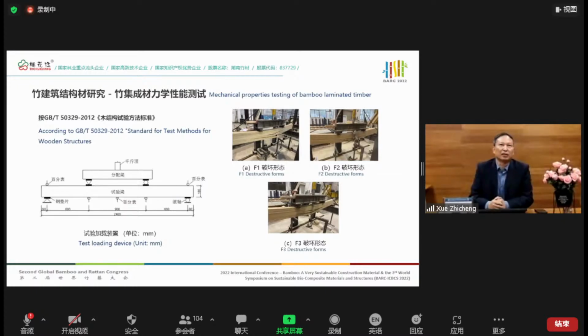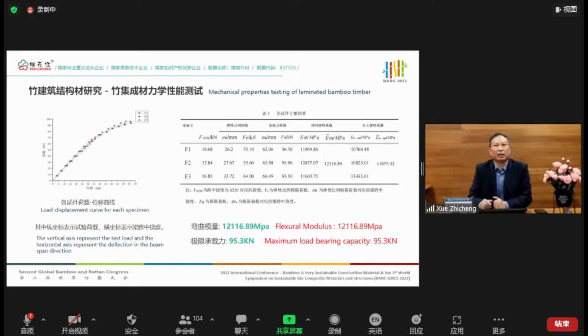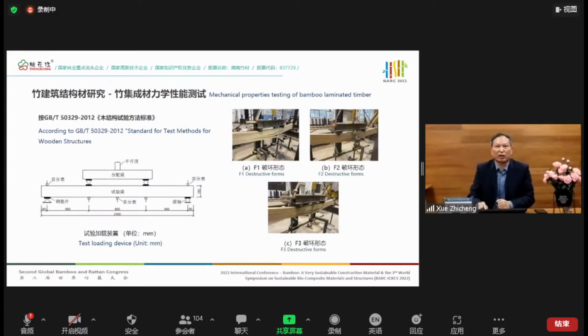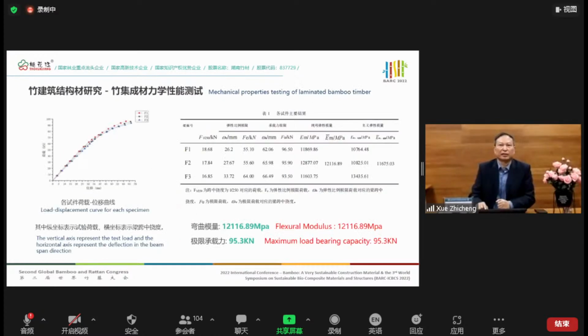So we also try to do mechanical testing of the laminated bamboo according to the GB National Standard 50329-2012, standard for the test methods for wooden structures. You can see the testing results. Very good result. The bending modulus can be 12,116 megapascals. Maximum load bearing capacity is 95.3 kN. Just some data. If you need the data, we can supply it to you later.